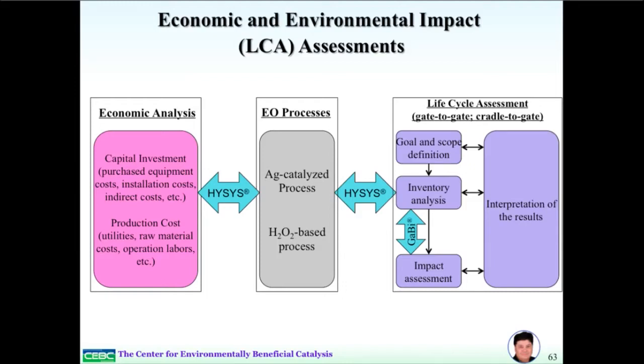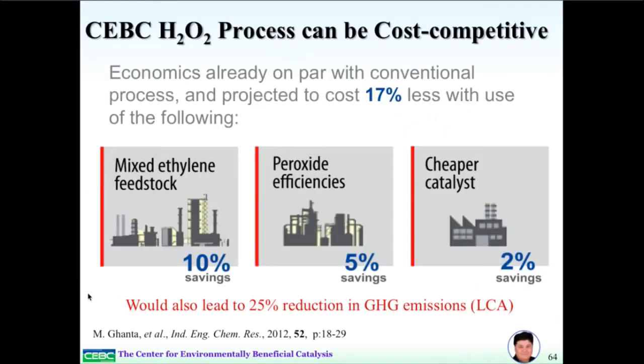So we can be cost competitive with a number of these. By looking at a few things, for example, going to a mixed ethylene feedstock. If you don't have to actually separate ethylene and ethane from each other, you save a lot of energy. You basically use the process itself as a separation process of ethylene and ethane. That'll save you about 10%. You can try and improve the efficiency of the peroxide and then look at working on a cheaper catalyst. If we do all of this, we believe we can get to a 25% reduction in the greenhouse gas emissions